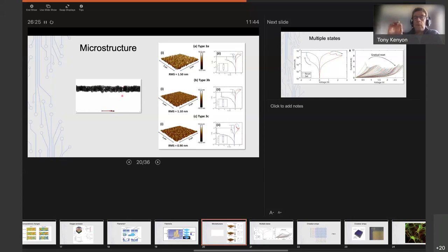So we thought, well, these could be regions where we form these filaments because they're defective. They're regions where maybe oxygen could move easily. And if we can control these, the density of them, the size of them, maybe we can control the electrical characteristics of the oxide. And it turns out that's exactly what we can do. So a very simple thing to do is vary this roughness, and that roughness templates the formation of these columns. If it's a very smooth interface, it's more difficult to form the columns. A very rough interface, the columns form very easily.